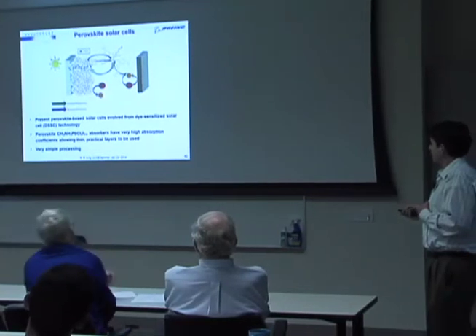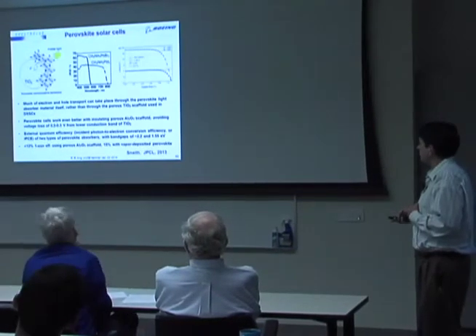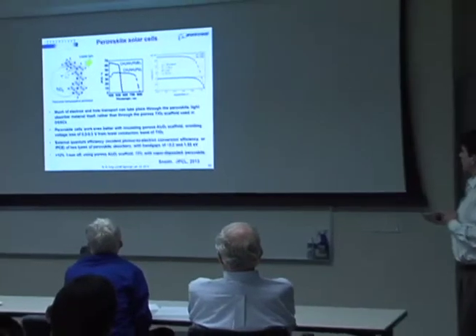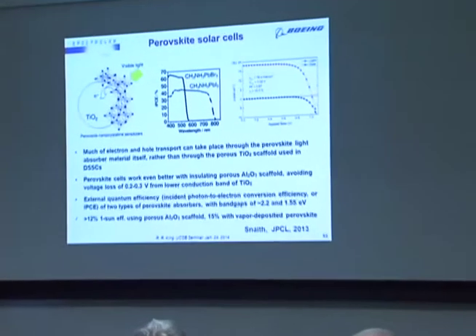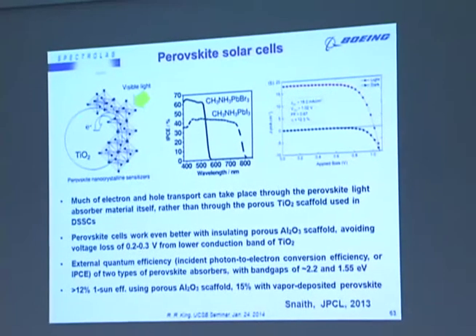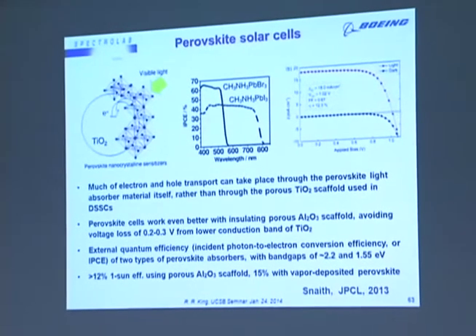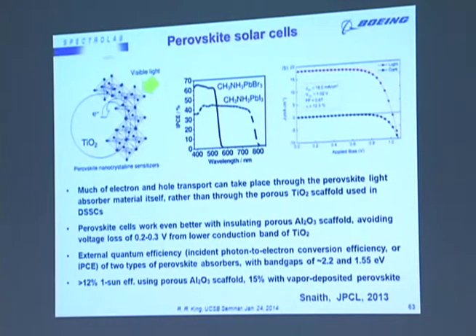These cells can have very simple types of processing. So again, I think I'll skip through some of this work, but in the perovskite materials, a large amount of the electron transport has been seen to go through the perovskite itself rather than into the titanium dioxide. And that's related to some of the very high efficiencies of 12% or so that have been seen.